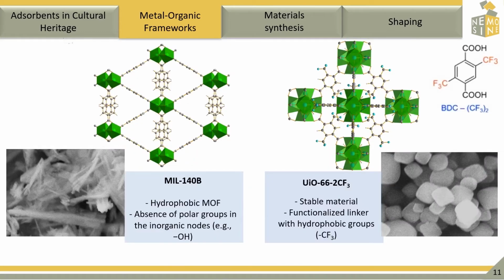So the high zirconium charge and elevated connectivity of the nodes accounts for exceptionally good stability of these materials, and the linker, the CF3, increases also the hydrophobicity compared to a non-functionalized structure of the UiO. So the two MOFs can be considered as hydrophobic, and they have been considered for the adsorption of acetic acid.